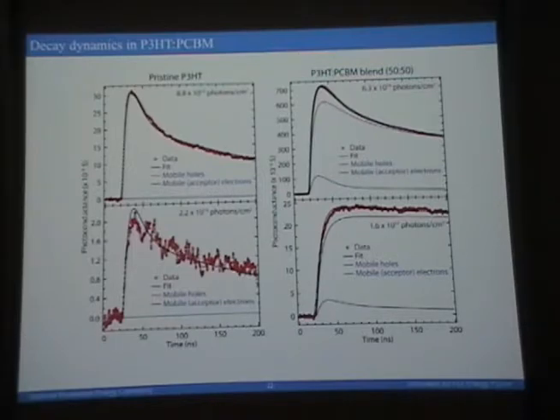And that's a key finding for us. Because what it means is that I can now detect clustering of PCBM. If I don't have clusters of PCBM, I get no electron signal, and I only see holes, just in the case of the polymer. If I have clusters of PCBM, I get a signal dominated by the electrons, because the electron mobility is high, and we have a high number of the carriers. So let's see how far we can push that piece of information.